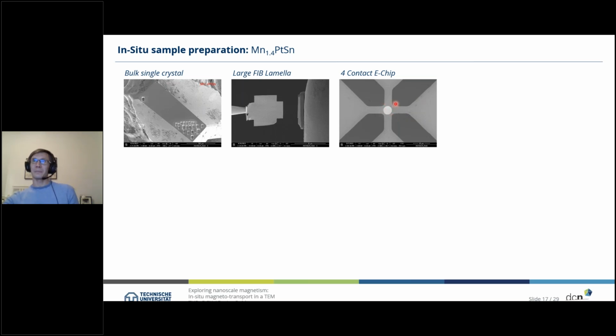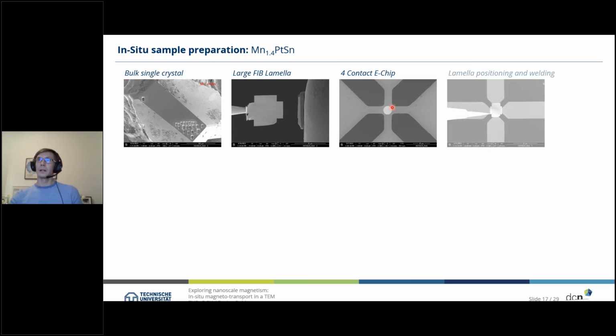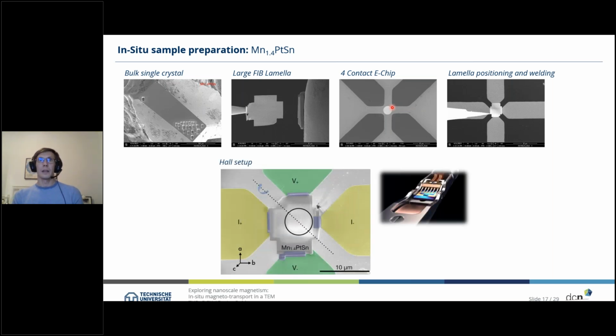All right, okay. So we cut a small hole in the center in order to have a better contrast later on for the Lorentz TEM imaging. And then we placed the lamella there and contacted it. And then the whole setup in the end looks like that, where we can apply the current in one direction and measure the Hall voltage perpendicular to that. And all that is then, of course, mounted in our transport holder.